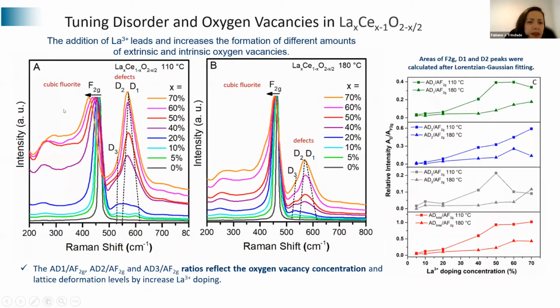asymmetry is increased in the samples synthesized at 110 degrees, and the defects are also very clear for the samples at 110 degrees. They are bigger than in the samples at 180 degrees. So this defect is attributed to the intrinsic and extrinsic oxygen vacancies. And then here, in more detail, when we take the ratio of the F2G peak and the defects, we can see the correlation and the lattice deformation by increasing the amount of lanthanum, and this was different for the methods such as 110 and 180 degrees.